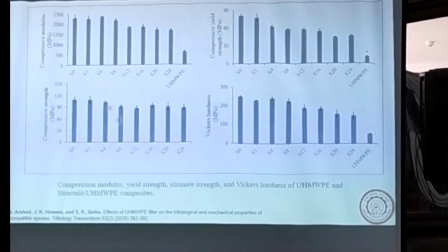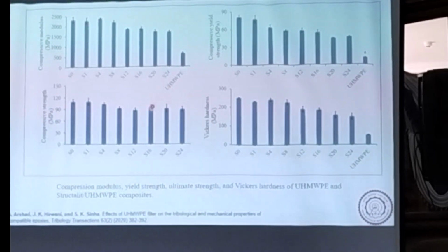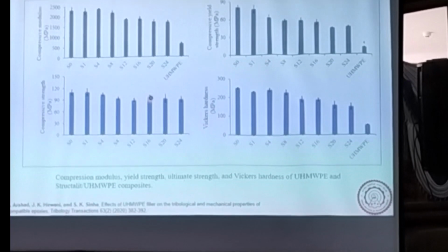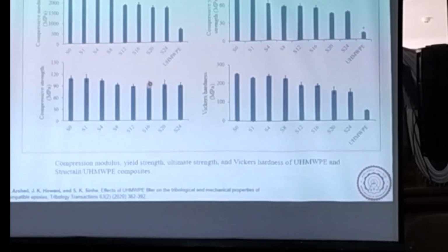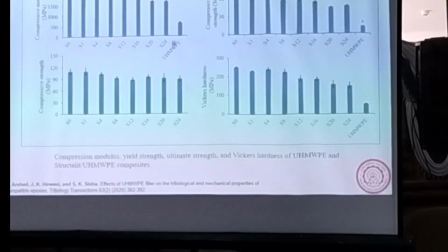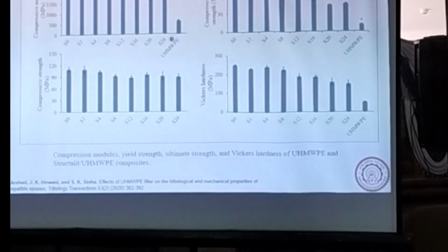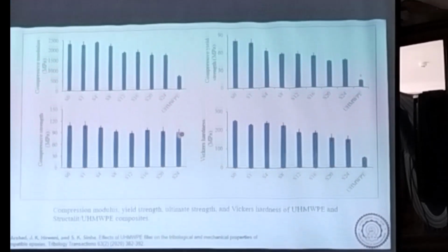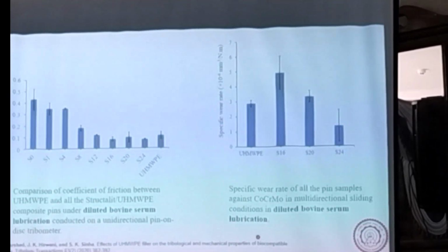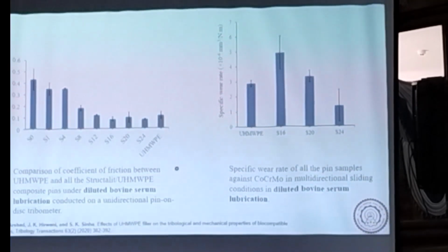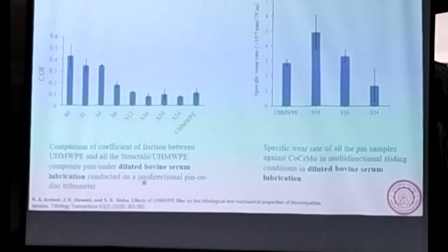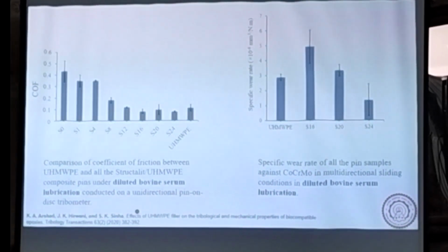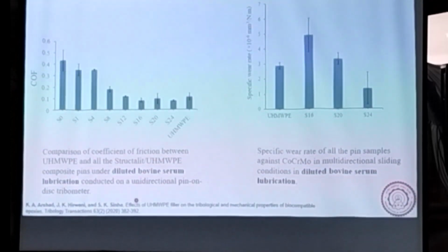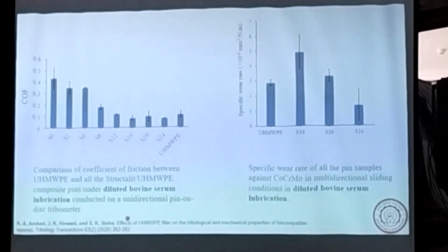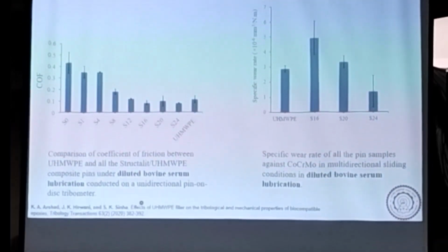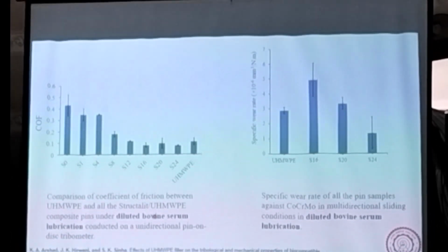So this data basically shows the variation of the mechanical properties for different percentages of UHMWPE. We did this as an optimization, and we found that perhaps 24% UHMWPE particle is a good composition for Structalit. And more important is this one, the tribological results, coefficient of friction and specific wear rate. This experiment was conducted in diluted bovine serum. Bovine serum is a lubricant that is used for this kind of bio-tribological experiment. It is not exactly what we have in our joints, synovial fluid, but it is quite close.